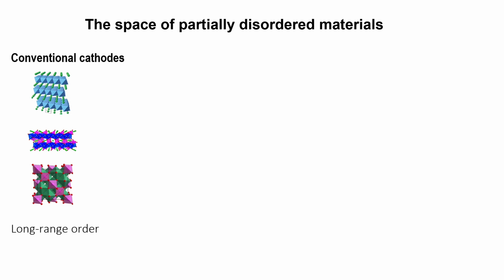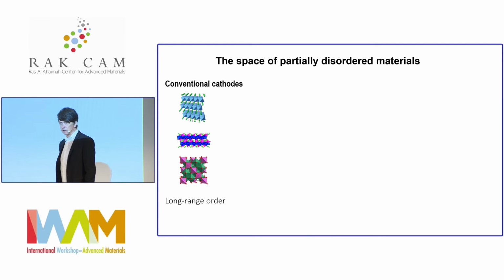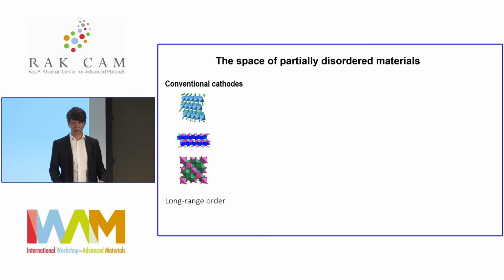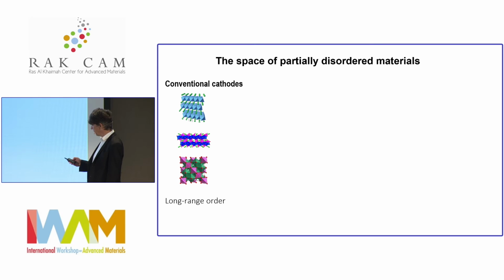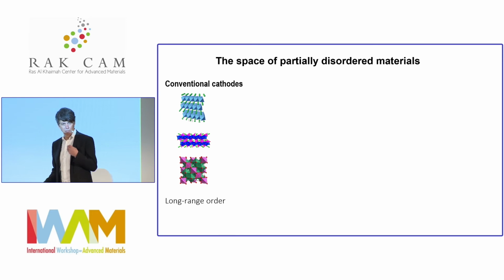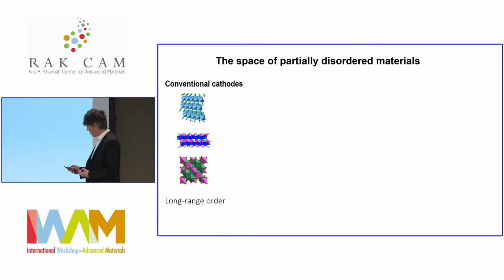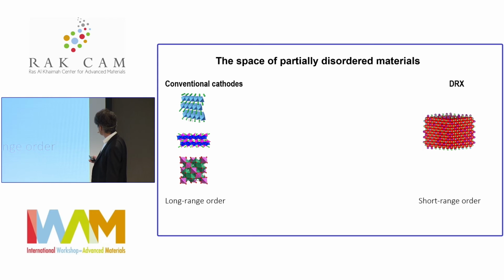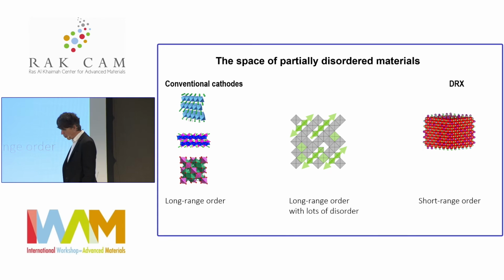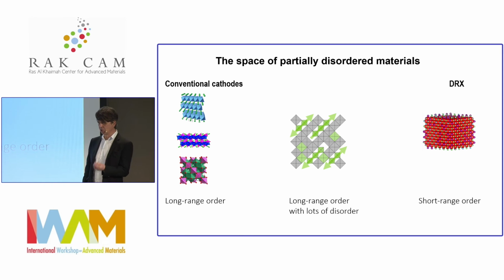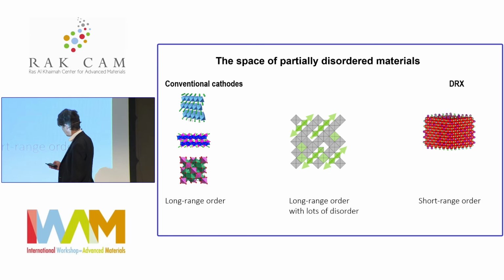But I want to end with a few slides looking forward, because I think this opened our eyes that there was a whole space of new materials out there that maybe was somewhat unconventional. For 20 years, the lithium-ion field, including myself, looked heavily into what I would call conventional cathodes. These were well-ordered materials, and if anything, we were trying to completely get rid of any disorder. And then we did fully disordered materials. So these are crystalline but cation disordered. That's the DRX class. And now I think if we work in the middle, where we have materials that are still long-range ordered, but with very high degrees of disorder, we can probably do even better. And I'm going to show you an example of that.